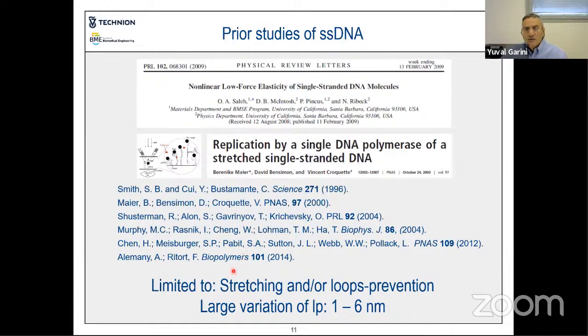limited, in the sense that in order to prevent those stem loops, those works were limited either to measurements where the DNA was stretched by applying force on the two ends of the DNA, but when you do that, of course, it also affects the persistence length, or by other means, like for example, increasing the salt concentration to an extremely high level, which is beyond the natural salt concentration inside the cells. And nevertheless, if you pick out the values that were measured, you can see a very high variability in the values that were reported in the literature from those works.